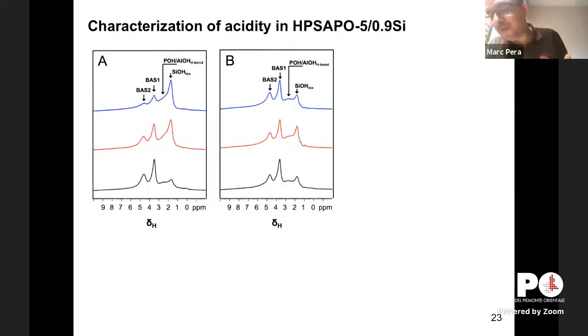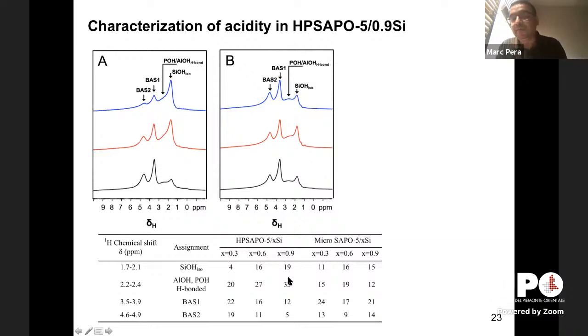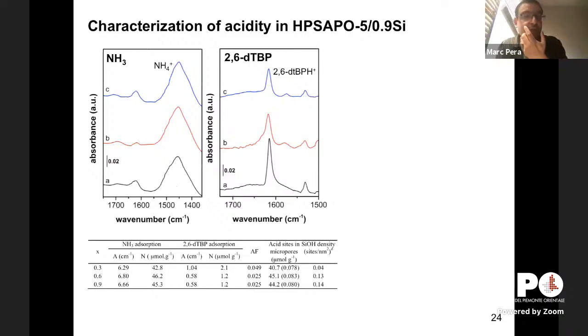Here, the colleagues of Italy were very skilled and helped us to characterize a lot the different types of acid sites and silanols that we have in our system. So we could characterize all the material. We have essentially two main acid sites in our sample that we could list and compare between microporous and hierarchical. So we have complete characterization. But what's very interesting is this test between using ammonia and sterically hindered pyridine that could allow us to distinguish between sites inside and outside the micropores. Just by doing some basic calculations between these two reagents, we can compare.